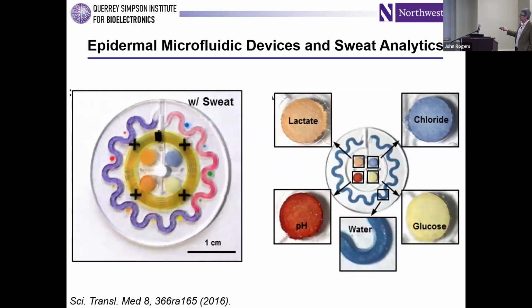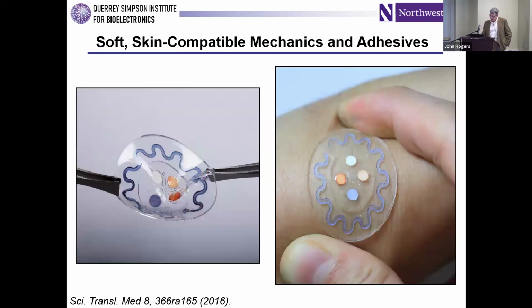This is the first platform of that type that we published. So it has 5 inlets, one in the middle, filling up this serpentine channel. We have a color changing chemistry here that goes from purple to red when in contact with water. So you just identify the color change front to determine how much of that channel has been filled up. You can determine the local sweat rate and sweat loss from that. And then there are 4 other inlet ports that connect individually to these 4 circular reservoirs, each one of which contains a color-changing chemistry that's responsive to a biomarker of interest, in this case, lactate, chloride, glucose, and pH. So it's a very simple device, single-use, recyclable, also compostable if you choose the materials appropriately, but providing quite a bit of information around sweat and, by extension, biochemical health markers and status.